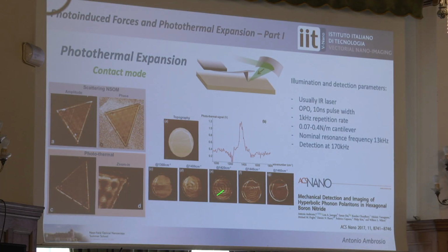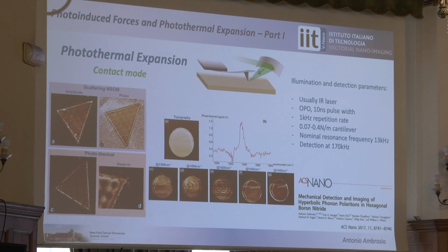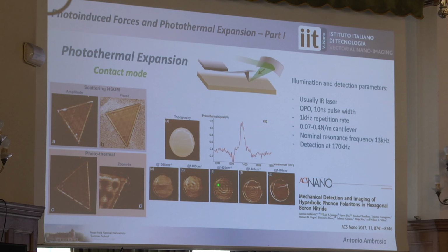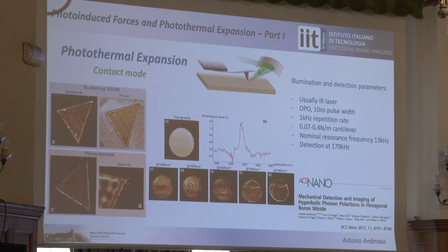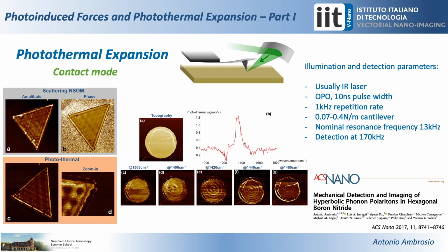So I tried again, just to be sure, with a different shape. And interestingly, if you do a wavelength change in a single position, far from any crest or valley, like this one right in the center, to probe hBN more, to be sensitive to the field, you see basically the phonon resonance of hBN. And as you change the wavenumber, you see different spacing in the fringes, looking really the same.